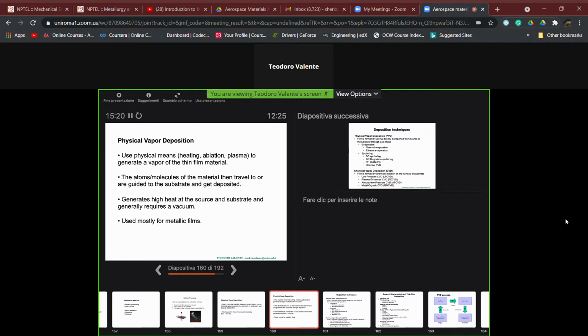Since we do have here the necessity to generate a vapor phase, starting, for example, from solid materials, which represent the materials with which we want to fabricate the coatings, we need energy to let the vaporization steps happen. And usually, in order to have a suitable value of partial pressure of the elements or atoms or molecules which will then deposit to form the coatings, this class of processes must be, and generally requires, vacuum.